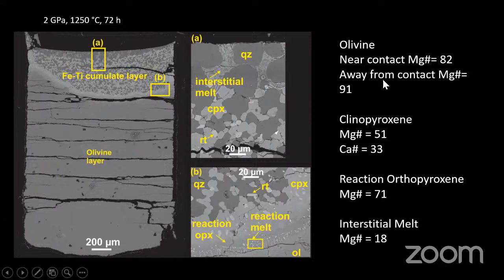Now, the major observation is that in the melt of this layer, the melts near the reaction zone are more Mg rich, which is expected because they are in diffusion exchange with the olivine layer, and the melts near the top, away from the reaction zone, are more Fe rich.